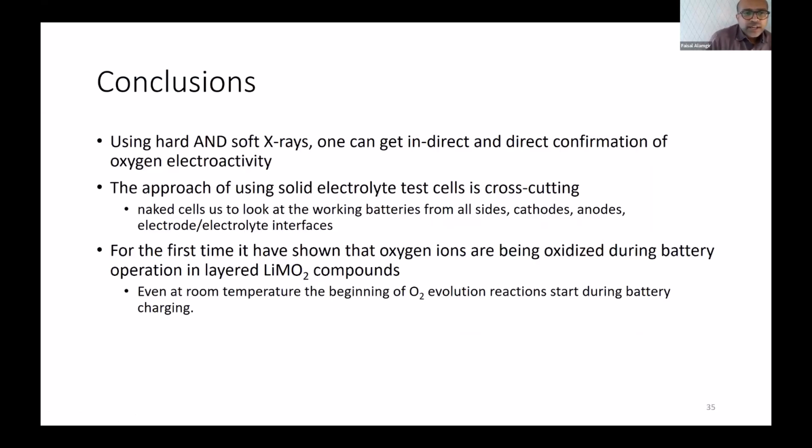I want to conclude by saying that if you can, try to design experiments where you take advantage of soft X-rays. Try to think through the kinds of things you are trying to measure and what each of those energy regimes will give you. There is always a trade-off, so you should try to do as many different things that complement each other. In this case, we demonstrated that if you use a solid electrolyte, you can look at the solid state reactions within the cathode materials without having to worry about the vapor pressure of a liquid electrolyte in a high vacuum chamber.